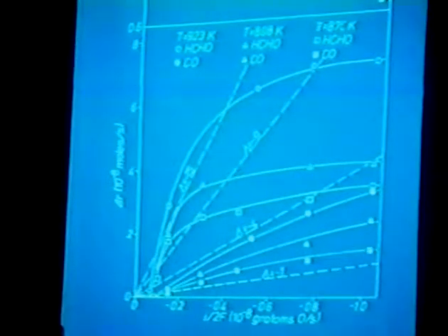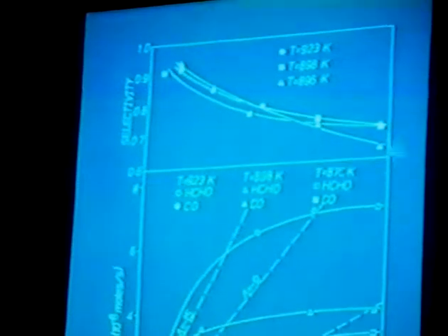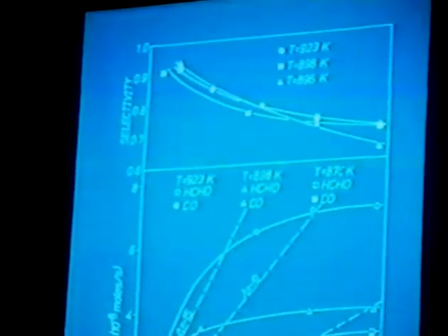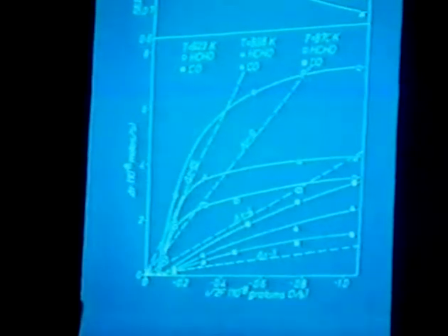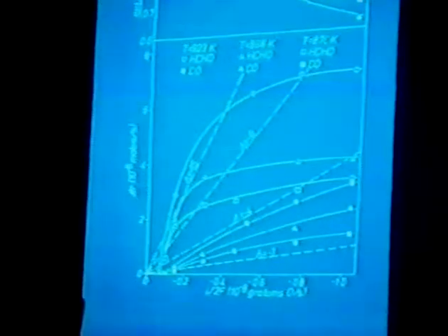Now, why are there some reactions where the rate is enhanced with an increase in the work function and others with a decrease in work function? Well, just to give you a very vague idea, let us look at the case of methanol decomposition on silver, where, as you see, with cathodic currents, with decreasing work function, we have a non-Faradaic enhancement in the rate of formaldehyde formation and CO formation. And as you go to more negative potentials, the selectivity to formaldehyde drops from 90% to 60%. We can qualitatively understand this behavior by noting that as you decrease the catalyst work function, chemisorptive bonds become stronger, so methanol is more strongly held to the catalyst surface, and therefore this enhances dehydrogenation and the decomposition.